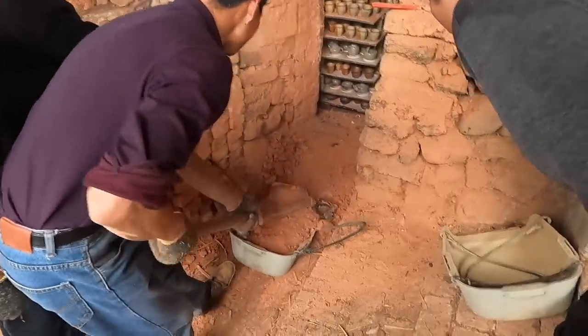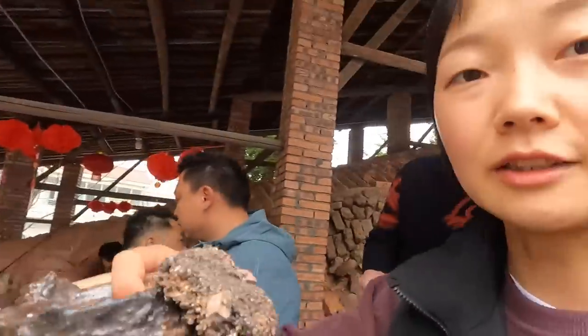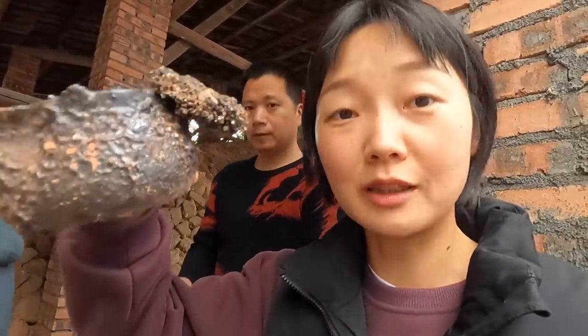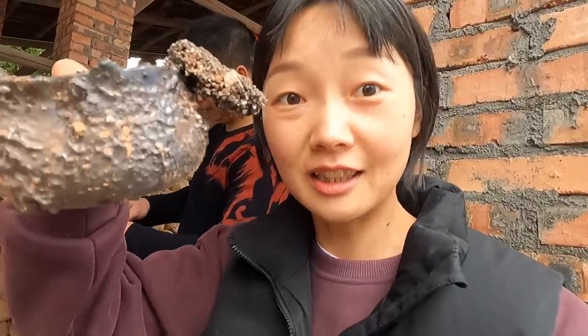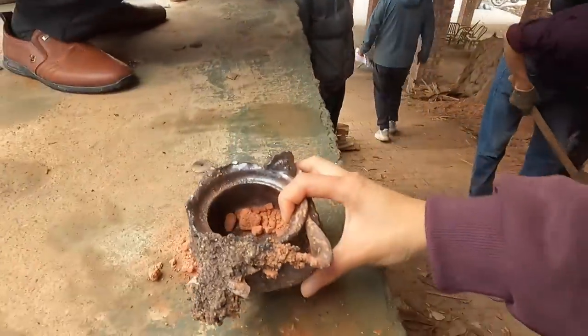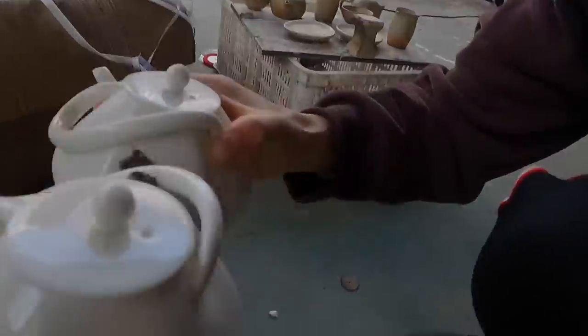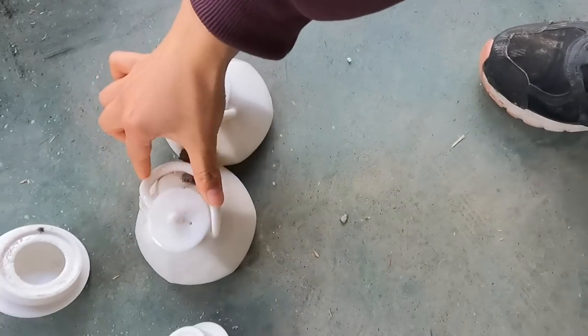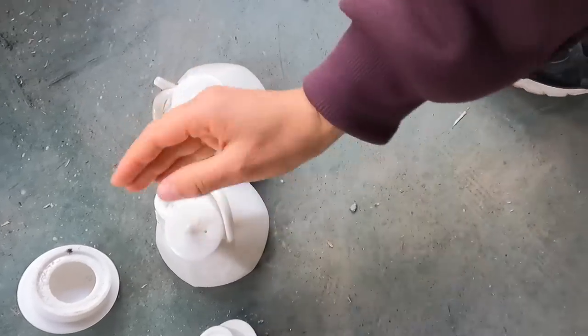And there's already broken pieces. Oh, it's still lukewarm, and he told me this is because the clay on the top of the kiln falls down and then got sticky in high temperature, and that's why this piece is defective. You know, those are also the ones that are filled. In that part, the handle needs to stand up, but because of the high temperature, it melted down.